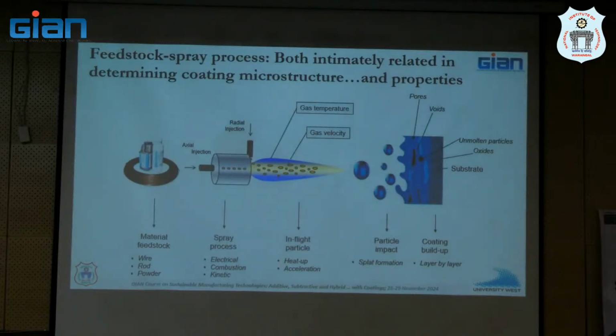All right. So let's come back to the same schematic in a slightly different way. Material feedstock, spray process. I said this is where the difference lies. How is the high temperature, high velocity zone created? There are typically three ways in which you create it. Sometimes it can be electrical. Electrical meaning you just strike an arc. You immediately create a high temperature zone. If you have two wires striking an arc, then you create a high temperature zone, and those wires themselves serve as material. And if you have a carrier gas, it takes away droplets from that and forms a coating. In some cases it is by combustion, this high temperature, high velocity zone, that is most common.